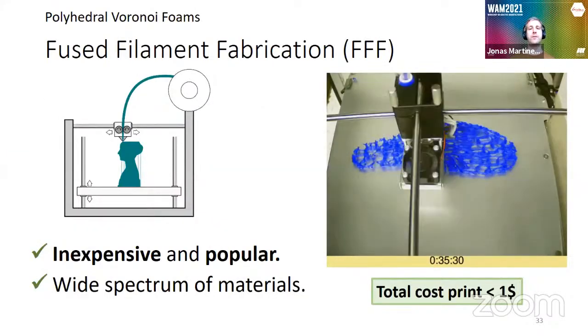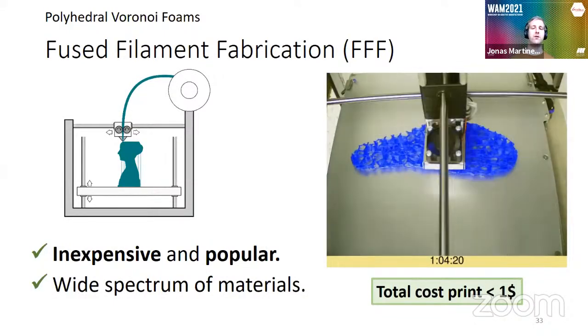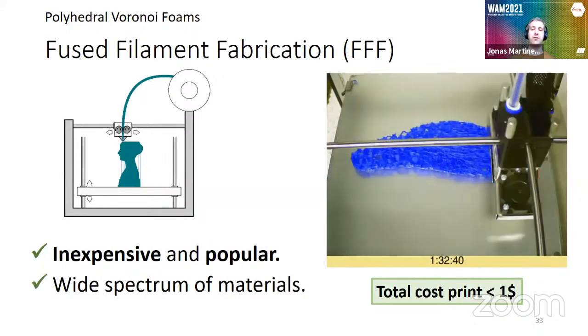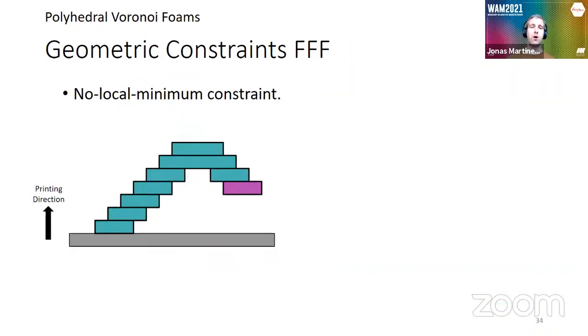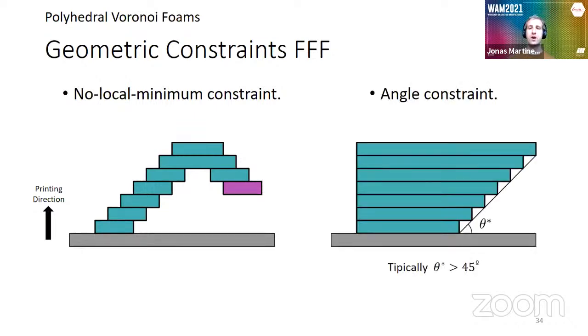So as I said, fused filament fabrication is a very inexpensive and popular fabrication technique, and has a wide spectrum of materials, so it's interesting. However, it has very strict constraints when you look at it from a geometric point of view. First, you cannot have a local minima, because of course, due to gravity, it will fall when you're printing layer by layer. And then there is a second constraint, which is usually called the overhang constraint, which tells you that when you're depositing one layer over the other, you cannot pass some limit of angle. Typically it's 45 degrees, but it can be others depending on the material.